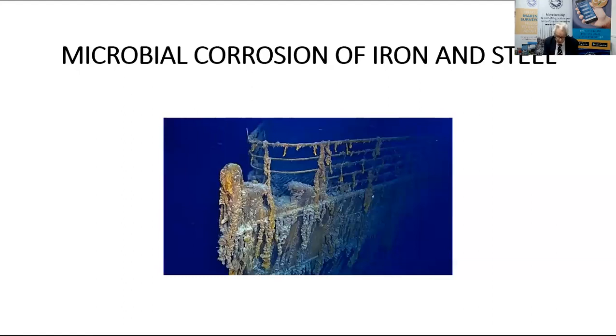The presence of the microorganisms has many complex and interrelated effects, and they can also generate environments favourable for the better known electrochemical processes to occur. They can, for example, destroy anti-corrosion additives, depolarize cathodic processes, and produce severe changes in local oxygen percentages that lead to differential aeration and concentration cells.